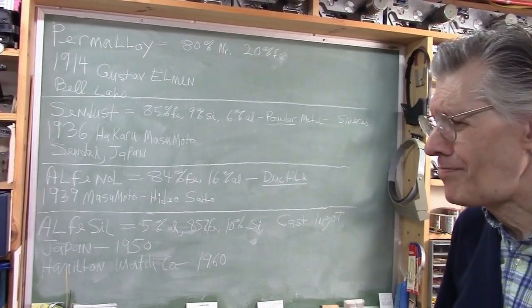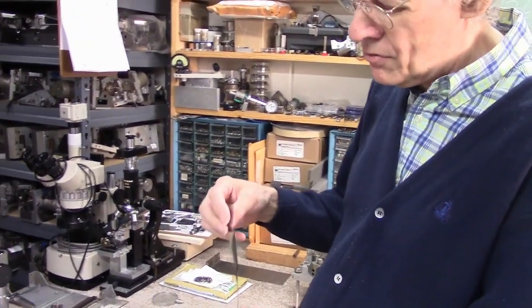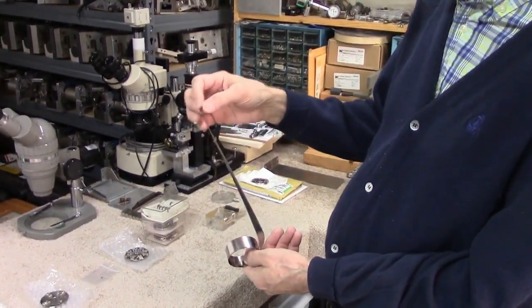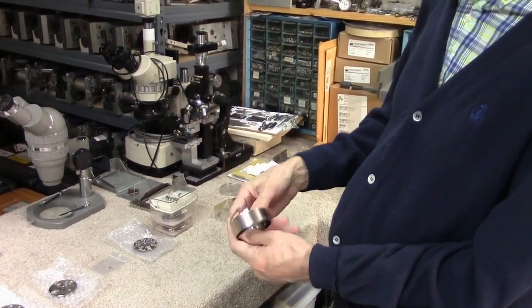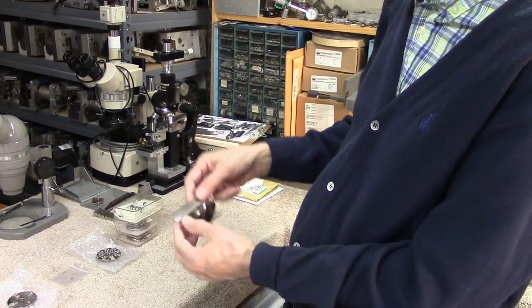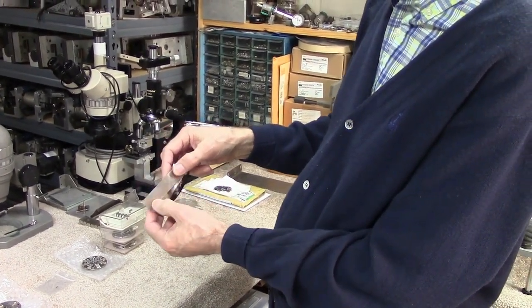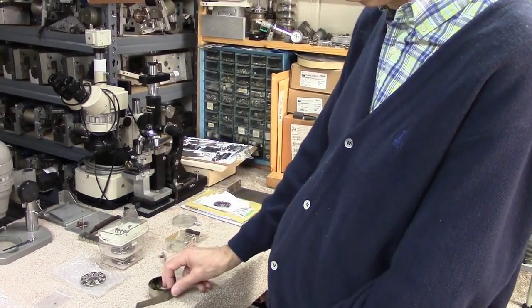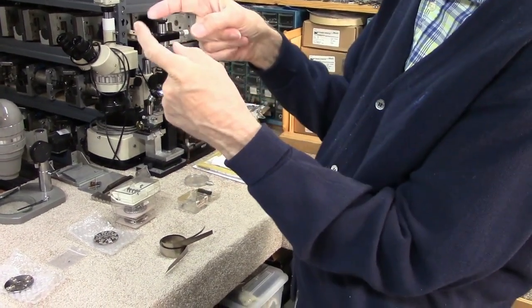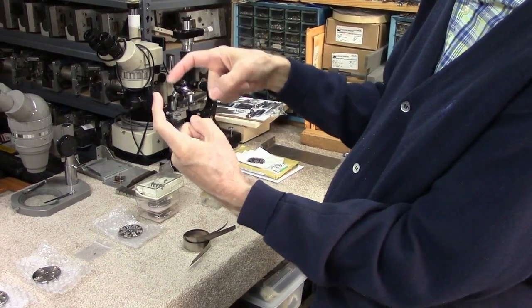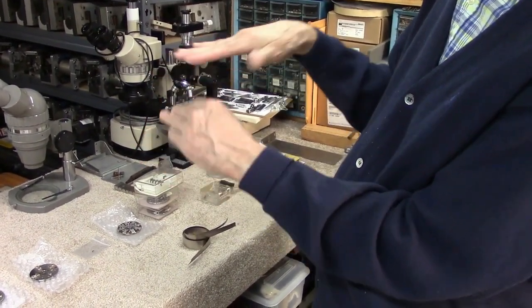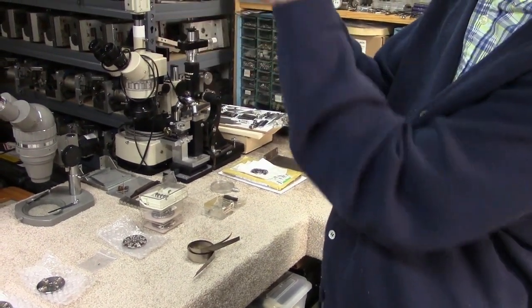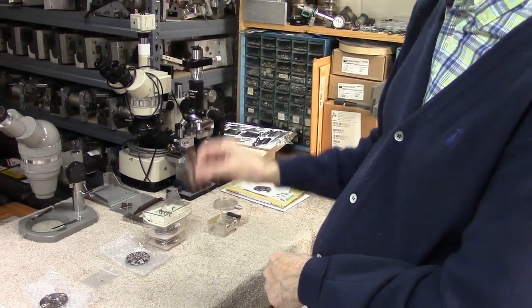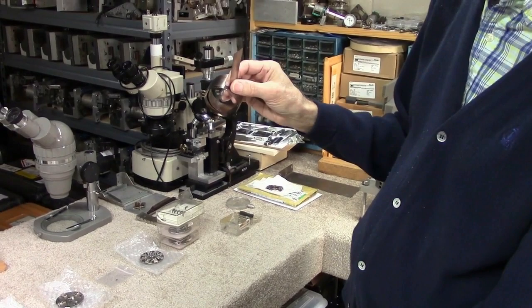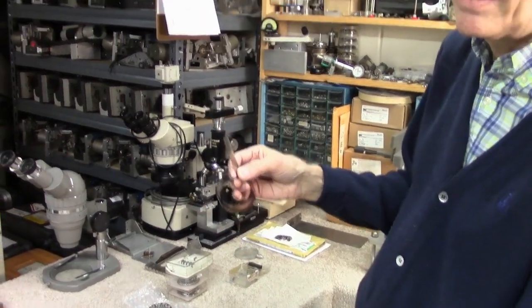And permalloy in that form, you would have rolls of permalloy. This is about 1 mil thick. And if you were making an audio head, what you would do is stamp pieces out of this strip of metal into your pole pieces for your audio head, and you would just laminate them one on top of the other and stack them up and build up a thickness of these laminations to the track width that you needed to make the head.